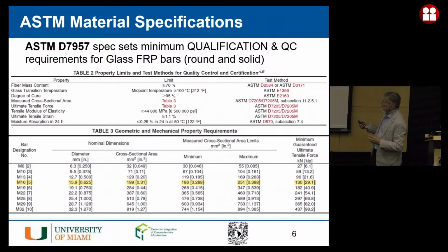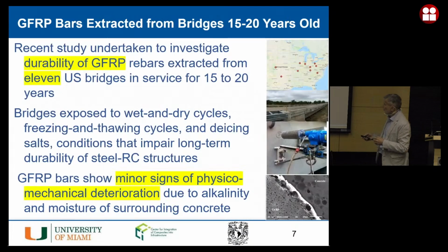D7957 tells you many things. Here I simply have a table to indicate that one of the interesting items is we define the maximum and the minimum size of a rebar depending on the denomination. So here you see in yellow an M16, a number 5 bar according to the US standards, and you can see what is the nominal diameter, what are the cross-sectional area, minimum and maximum sizes, and then what is the guaranteed ultimate capacity. And this is measured as average minus 3 standard deviations. So very, very stringent requirement.